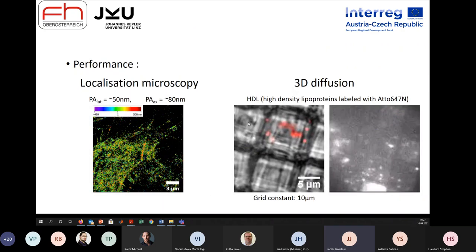And now what we have done, as I mentioned, we wanted to look at single molecules. So we wanted to observe the transport processes at a single molecule level. And what we nicely were able to show is that we can perform localization microscopy. This is a technique which enables us to localize single emitters in 3D with a precision in the tens of nanometers range, so 50 nanometers lateral localization and 80 nanometers axial localization.